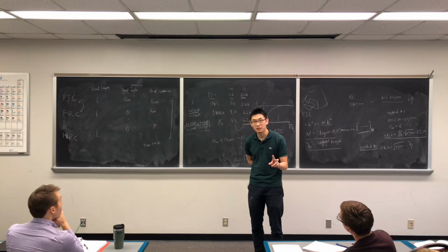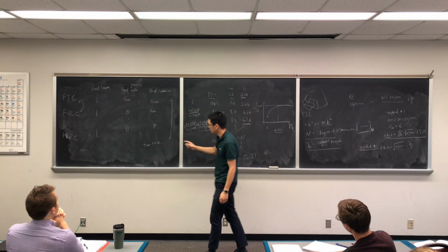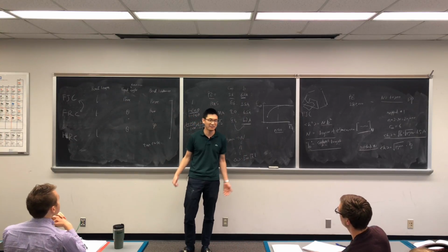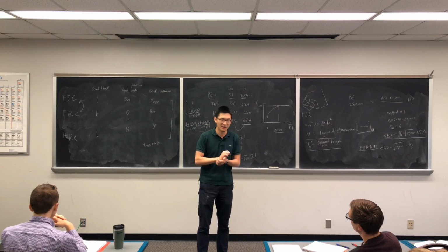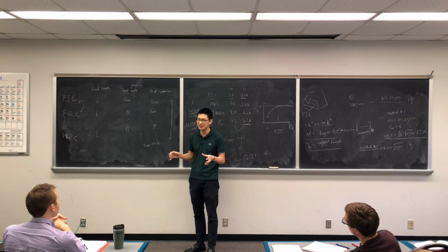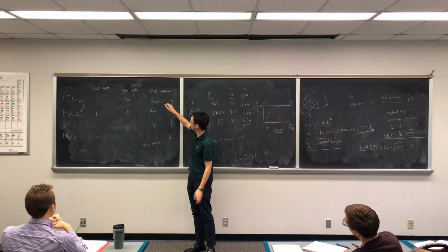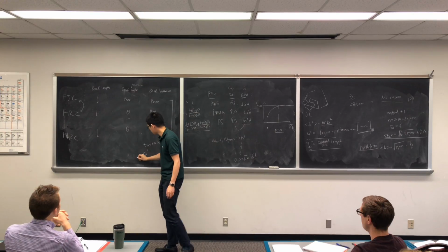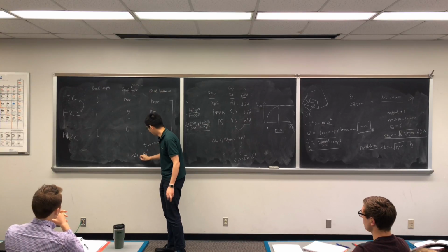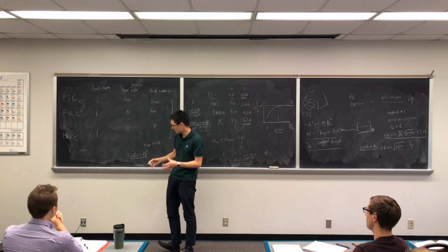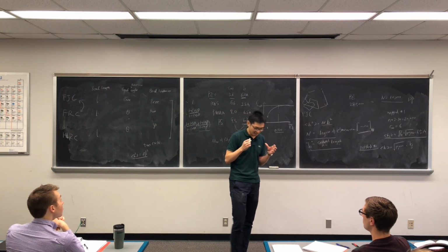So, let me explain 2 different cases. They would never behave like a free joint chain in a real case because, I mean, it's just anti-physics that 2 bonds can sit in the same position. What we mean here, using free joint chain to describe these 2 cases, is that the end-to-end distance, what you get measured experimentally, agrees with n l squared. Let's first be clear about that. So, if the results match, or your chain happens to be that way, we call it a special condition.